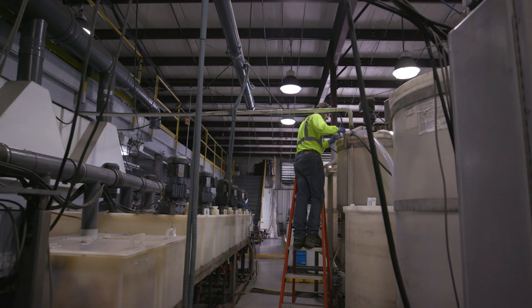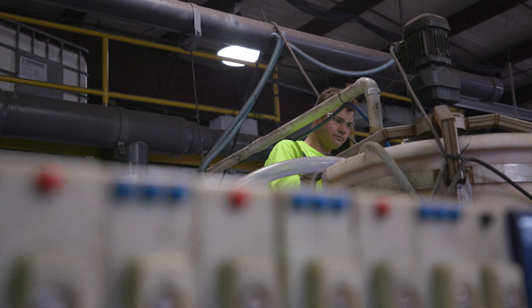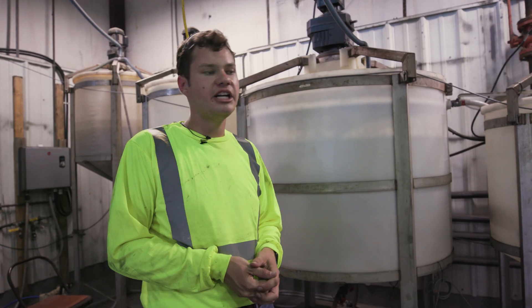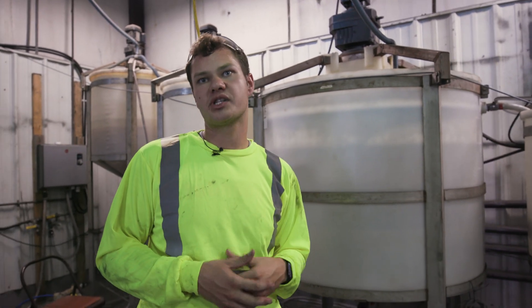For the last few weeks we've been working a lot with acid mine drainage — very acidic water that is flowing over coal waste and basically leaching out rare earths into solution. It's very valuable for us to work with, so we have shipped roughly 5,000 gallons in here. We've been slowly increasing the pH in different increments to get out what we don't want, and then to get out the rare earths as our end goal.